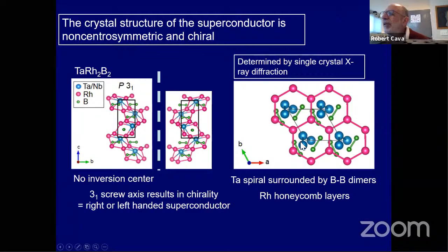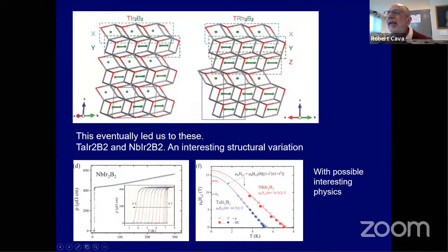So that's a screw of tantalum, a 3-1 screw of tantalum. And that chirality is maintained. So unlike some structures where you have a screw going one way and then the one next to it goes the other way, these all go in the same direction. So the thing is a chiral lattice. And so those are the rhodium ones.